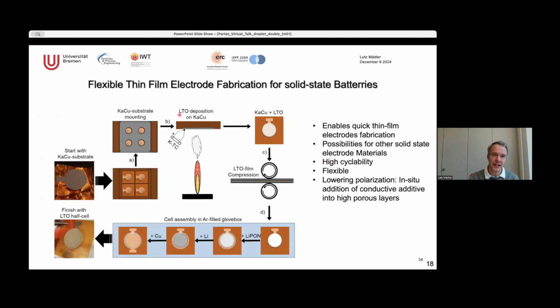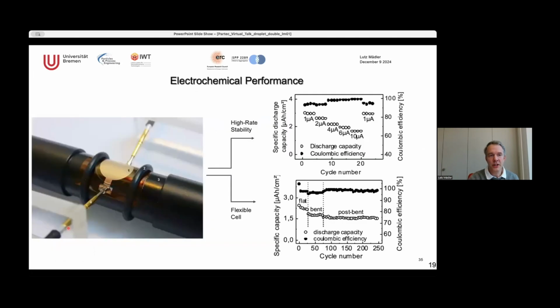So we did exactly this. We deposit our particles in a dry form. So they don't need to be dried, they don't need to be sintered, nothing. On the electrodes, we made a little cell out of this. Again, this is a collaboration with Fraunhofer IFAM here in Bremen. And then we start bending because we thought that this is flexible.